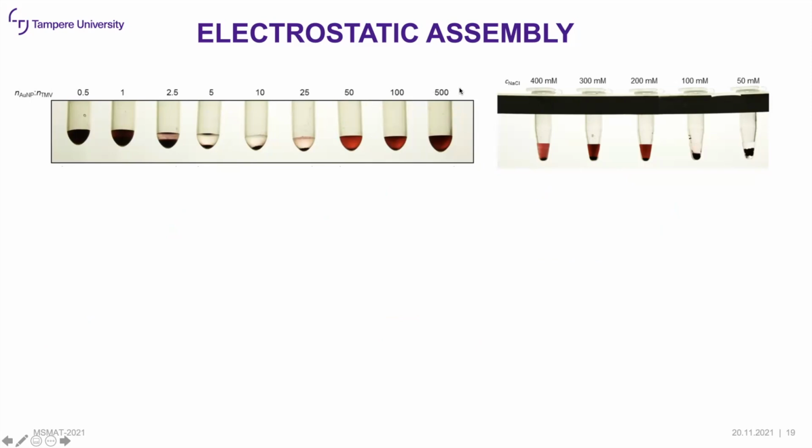We go up to 500. But an optimal concentration we found, from nanoparticle to tobacco mosaic virus, is between 10 and 25. If you take one of these and then start to decrease the ionic strength, here is the high salt concentration. You don't see any assembly formation because if you look at the excess gold, the color is still the same. But the moment you start to decrease the ionic concentration, something precipitates out.